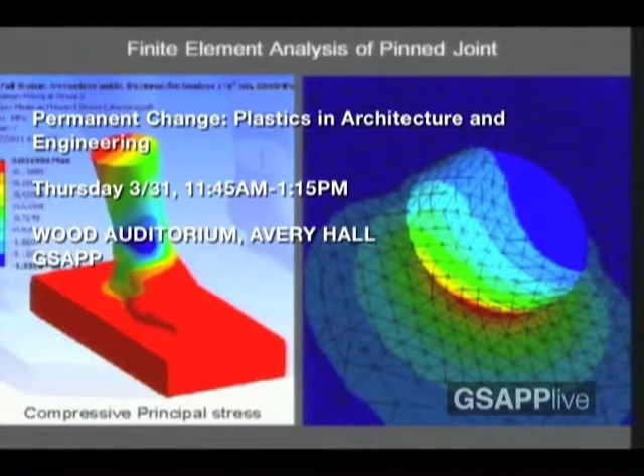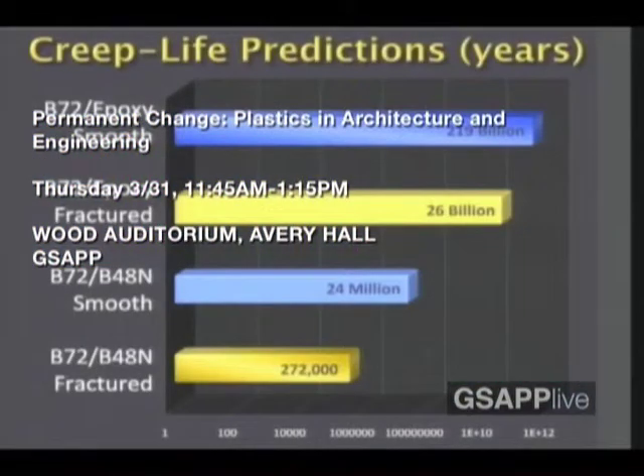we finally, after looking at all of these pinning strategies, have decided to simply glue the joints back together rather than introduce any pins. In part, we learned that drilling a hole in a piece of marble to introduce a pin brings about a tremendous flaw in the system, and that is very susceptible to breaking at the end of the hole where the drill hole was made. So we've decided and explored a whole range of different glues to put this back together.